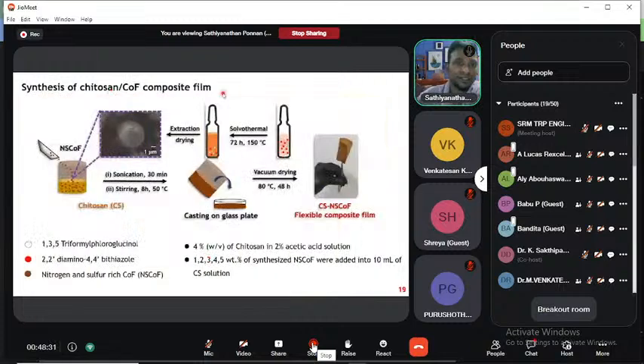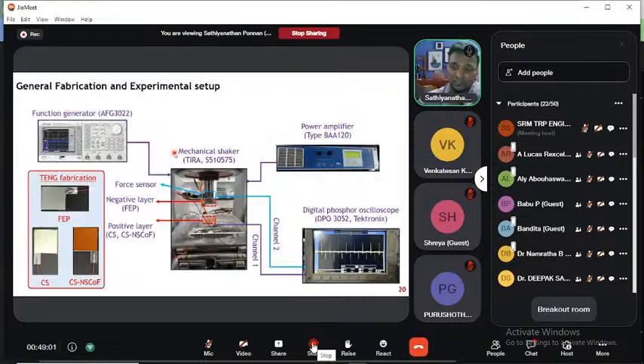So how did we fabricate the composite? After the synthesis of CoF, we incorporated it into chitosan at different weight percentages, 1, 2, 3, 4, 5 weight percent of the CoF system, and we fabricated a freestanding film which is flexible in nature. Actually, it is very difficult to achieve a freestanding film using chitosan. So we worked on it, did many trials, and finally achieved this.